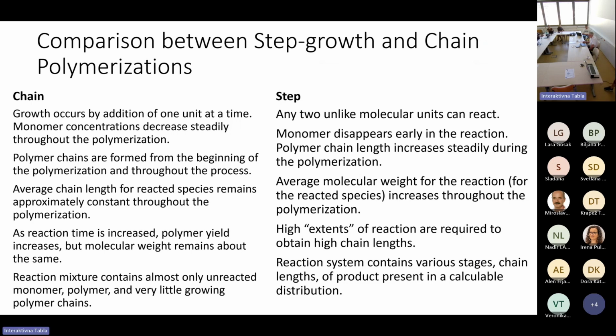In step polymerization, high extents of reaction are required to obtain high chain lengths. In chain polymerization, the reaction mixture contains almost only unreacted monomer, polymer, and very few growing polymer chains. While in step polymerization, the reaction system contains various stages, with chain lengths of products presented in a calculable distribution. So that is the comparison of these two polymerization mechanisms.